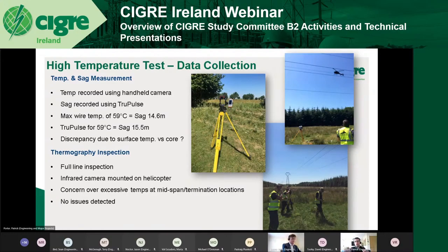And that's discussed in a lot more detail in the paper and the report, but it essentially came down to discrepancies between conductor core temperatures versus surface temperatures, which is quite critical, particularly when you're dealing with high temperatures such as this, well in excess of the ambient temperature on the day.